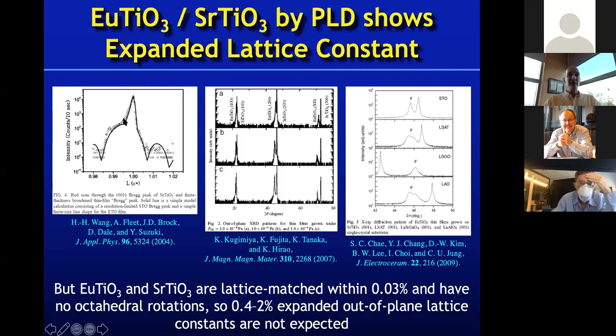But you can clearly see it. Here you see the thickness fringes from the film. This is my colleague Joel Brock here and Yuri Suzuki, at the time at Cornell. The film peak is here. The substrate peak's there. If you look at this other group, here's the substrate peak, the nice intense one. Here's the film peak.